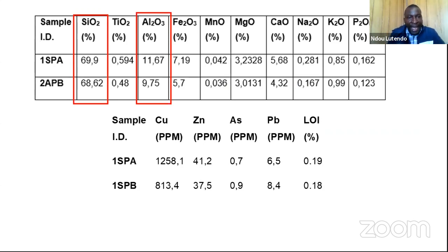And I highlighted silicates and aluminum oxides, so that you can see that these materials had more content of aluminum silicates when they are combined together. And that gives us over 80% of aluminum silicates. But also, I had to look at the elements that were there.